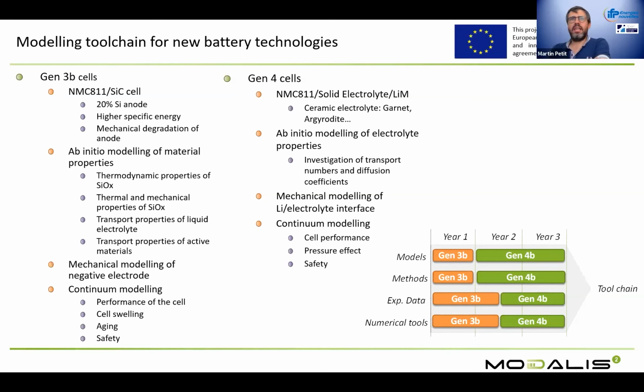So in order to characterize and analyze this behavior, we will have some ab initio modeling of the material properties in order to get the thermodynamic properties of the silicon oxide, our material for the negative electrode, the thermal and mechanical properties of the silicon oxide, and the transfer properties in the liquid electrolyte, as well as the active material. Then, thanks to this data, we'll be able to perform a mechanical modeling of the negative electrode, giving the swelling of the electrode as a function of state of charge, of C rate, and of the constraint on the electrode. And finally, we apply these two lower level modelings to the continuum modeling in order to assess the performance of the cell.